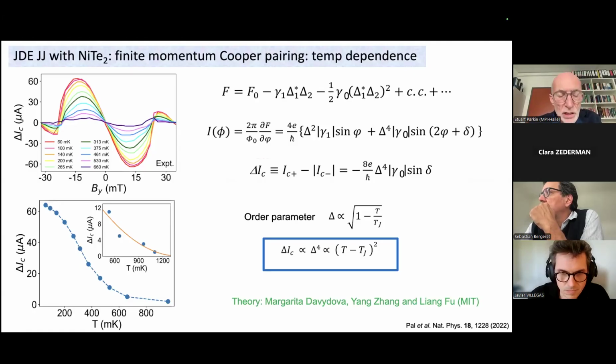And you can see here very nicely that they predicted that this diode effect would vary as the temperature minus the temperature at which we form by proximity the superconducting state, in this case nickel ditelluride, to the power 2. And this is, in fact, what we find experimentally, as you can see on the bottom left. Here is the difference in the critical currents as a function of temperature, and the red curve shows this T minus Tj to the power 2. So we could explain basically all aspects of our experimental data, in particular the temperature dependence of the asymmetry in critical currents, as well as the dependence of this asymmetry on the magnetic field.